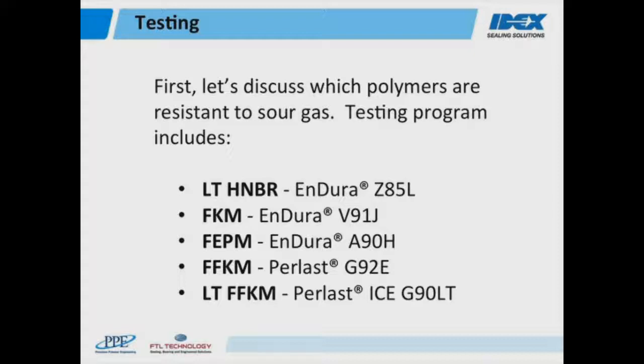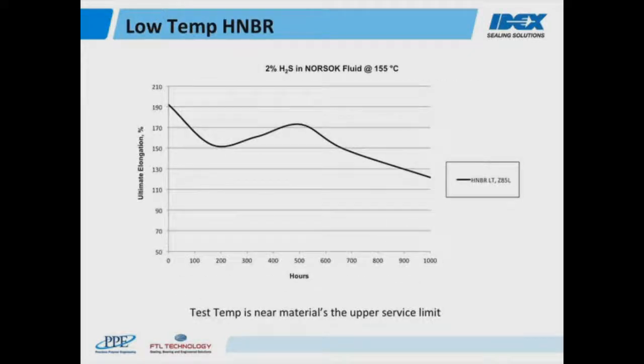The first test I'll show of a material in a sour environment will be a low temperature HNBR Z85L. It was tested near its high temperature service limit, and then the next slide will show the higher temperature materials. The test generally follows the NORSOK M710 Annex A protocol. The test specimen is immersed in a multi-phase mixture containing a gas component, hydrocarbon mixture, and water.